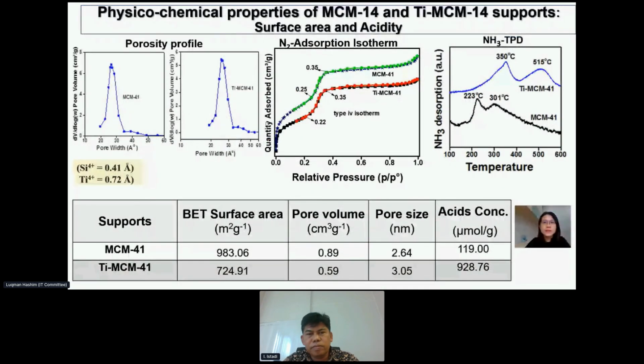So next, we look at the textural profiles of the modified support, and both supports show type 4 of the adsorption isotherms from this BET analysis. This indicates the mesoporous nature of the materials, and we can find that there's a slight difference between the pore diameters, which is pore size, where the modified MCM41 shows a larger pore size as compared to the pure MCM41. Okay, so this is due to the incorporation of the titanium into the hexagonal structures of the mesoporous silica MCM41, and that's why it leads to the widening of the mesopore for the Ti-MCM41, because of the larger ionic radius for the titanium species as compared to the silica species here.